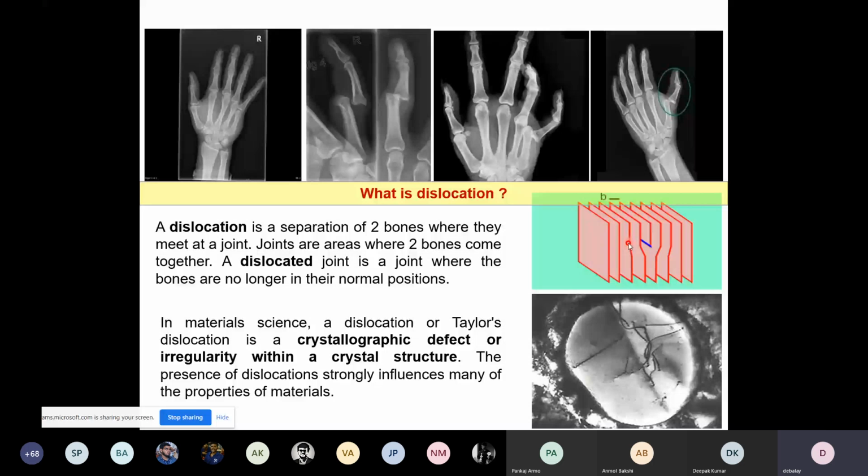And we have shown that dislocations look like these hairline defects in transmission electron microscopy because the lattice plane shifts near the dislocation, and from that location the electrons get diffracted, whereas at other locations electrons get transmitted. So you see that part as a dark line, but sometimes if you tilt the specimen, you may not be able to see this line. Some other line will appear, a dislocation line, because how your specimen is oriented with respect to your electron beam is also important.